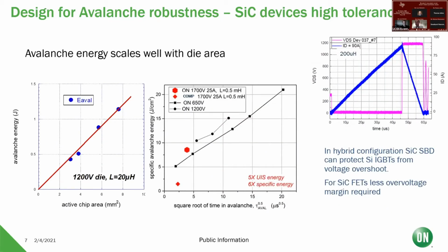There are features that are intrinsically better. This one talks about avalanche energy being much easier to handle in silicon carbide. Therefore, the kind of overprotection that is typically needed for a silicon device. In fact, a silicon carbide diode can provide that function in support of an IGBT. But if you just purely design with a silicon carbide FET, you need much less overvoltage margin and can handle these things, especially with a little bit bigger die. Obviously, everyone wants a minimal die, but we have some cushion there in terms of absorbing the high energy that comes with avalanche breakdown.